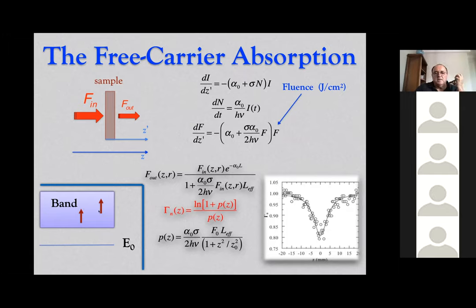But if this is due to a large number of photons interacting with your material, the fluence that we make incident on your sample and the fluence outside the sample will depend on different parameters, sigma and alpha. Alpha is the linear absorption. The sigma here is due to free carrier absorption. It's not an absorption between two different levels, but inside a single band.